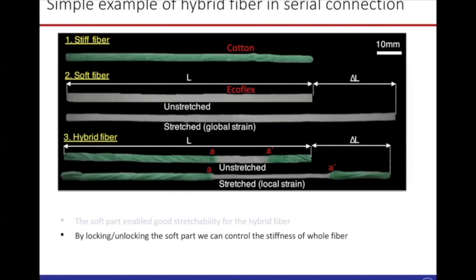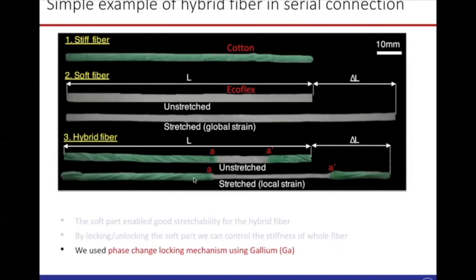So we propose using a locking mechanism using a phase change material called gallium, which is a low melting point metal. So we are planning to introduce a locking mechanism inside this soft part using this gallium to lock or unlock the soft part. In that way, I can control the stiffness of this hybrid fiber. Now, this is just an example of a hybrid fiber. The actual fiber looks different.